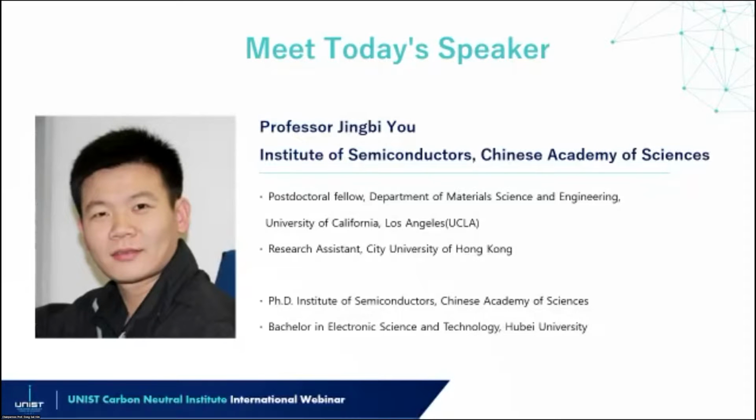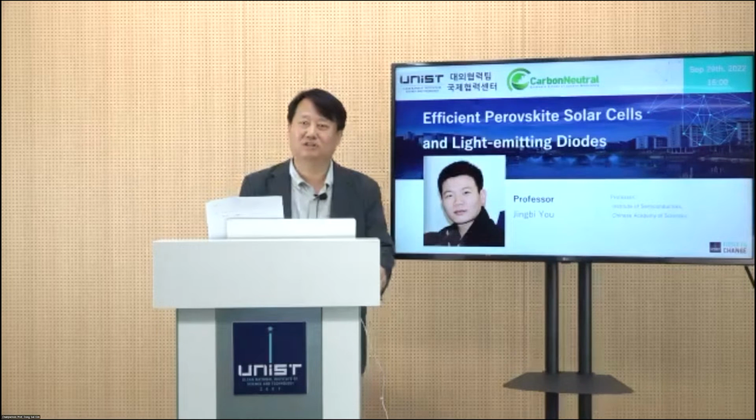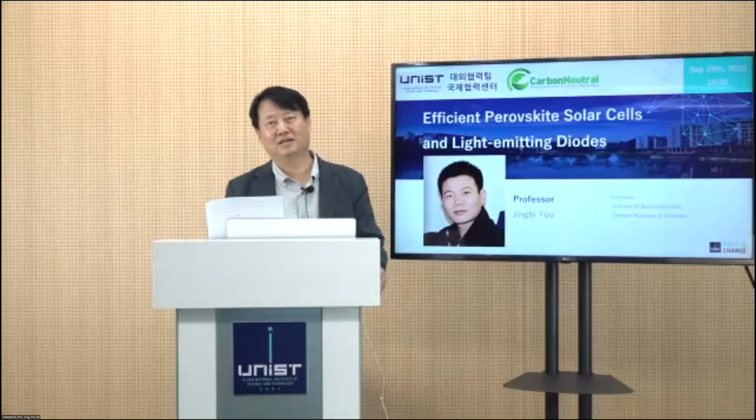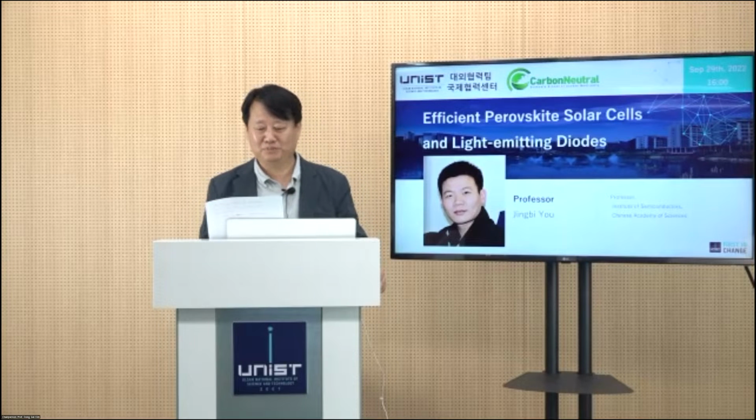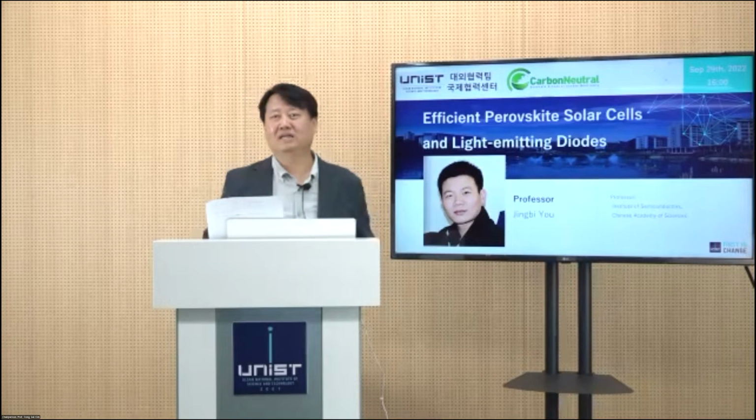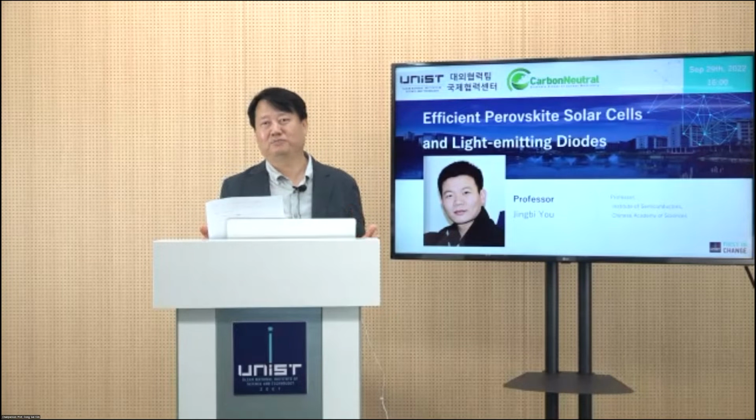His first outstanding achievement is the introduction of a passivation layer using PEAI. PEA means phenylethyl ammonium iodide. If you use this kind of passivation layer, you can reduce the defect density associated with iodide vacancies, so it increases the VOC and fill factor to make high efficiency perovskite solar cells. So this is a very powerful method until now.